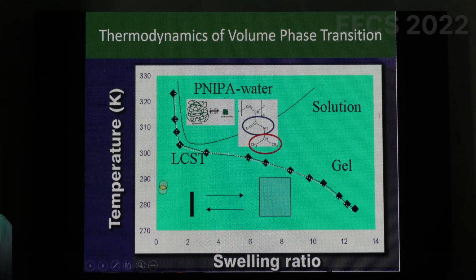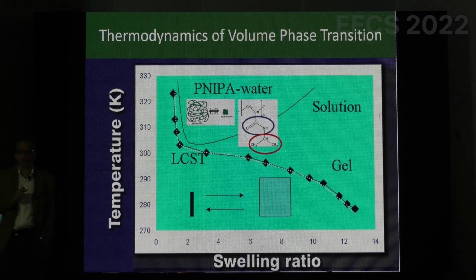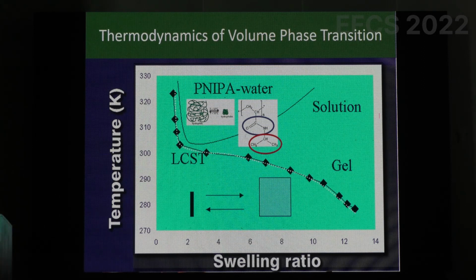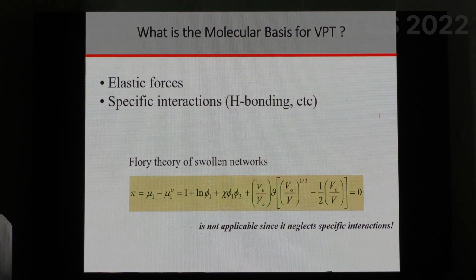So very low swelling ratio at high temperatures, that means the gel collapses, throws water out, and as you start decreasing the temperature, the swelling ratio increases, so the gel swells, right? So this transition is called the volume phase transition, right? It's volume because it grows, it expands in volume and collapses in volume, and it's a thermodynamic change, and that's why it's called a phase transition, right? So that's the origin of volume phase transition.